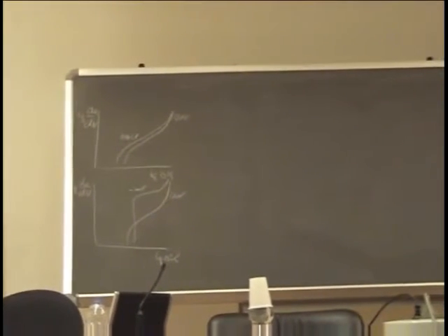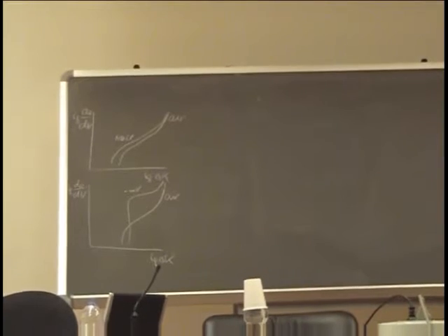So this was very interesting. And in the end, it was even dependent on the thickness of the specimen. Thinner specimens had a larger effect, thicker specimens a smaller effect. Obviously it was the transport from the side surface of the specimen to the interior along the crack front, because it's the crack front that matters. And unfortunately, we had to stop this due to the lack of funding. It was very, very interesting.